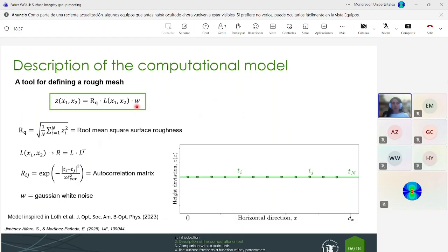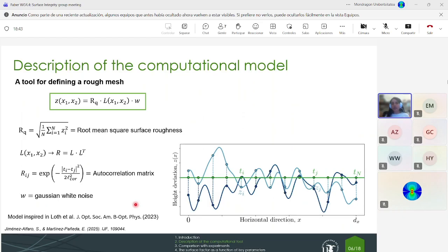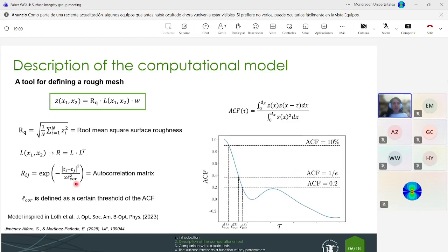So if we introduce one Gaussian white noise, then we have a certain profile. And if we introduce another one, the surface profile is completely different, considering the same parameters, the same root mean square surface roughness and the same correlation length. About the correlation length, it is an additional parameter that is here in the definition of the autocorrelation matrix. This parameter is quite interesting because it defines how the different peaks are related in the horizontal direction.